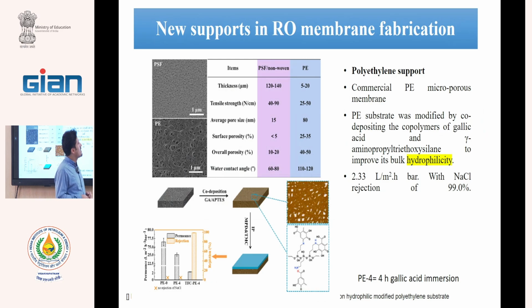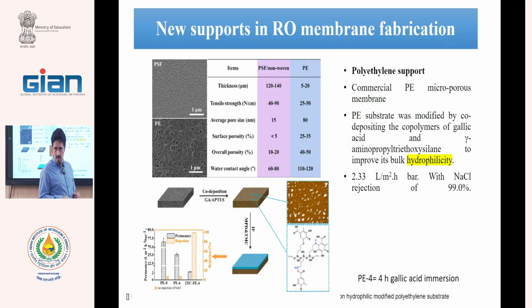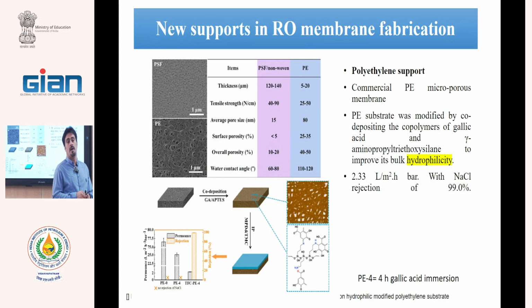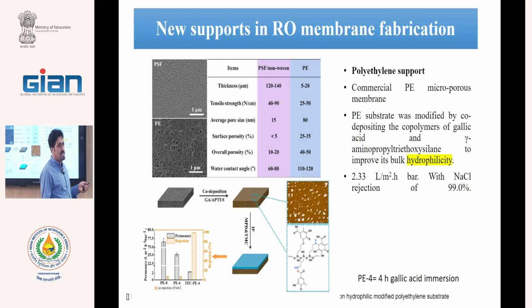Polysulfone is 50% of the price of the RO membranes. Polysulfone costs about $100 per kilo, but polyethylene costs $2 per kilo. $2 versus $100. If we can use polyethylene polymer instead of polysulfone, the price of the RO membranes will be very, very